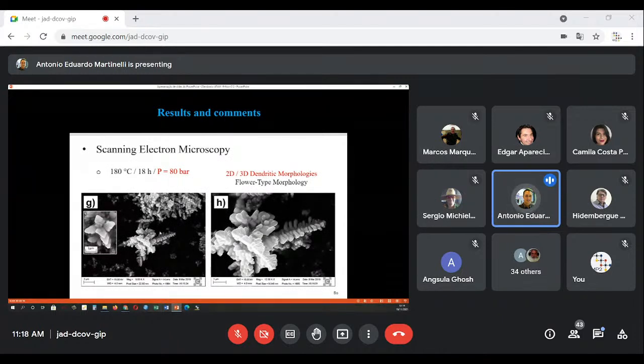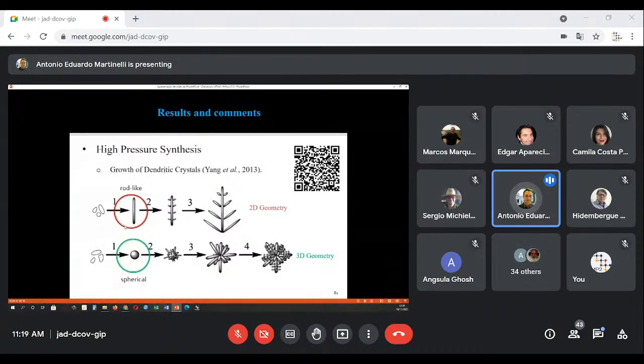At 80 bar, we see both 2D, two-dimensional, and 3D, three-dimensional, dendritic morphology, both from the flower type morphology, which can be explained by where the particles start to grow. If in the beginning of the nucleation and growth we obtain rod-like particles, then they grow in the 2D geometry. But if in the beginning of nucleation we got spherical particles, then the spherical particles grow and achieve a 3D flower type geometry. These results can be seen in the work by Yang, which you can reach by taking a picture of this code, and it will take you directly to this work.